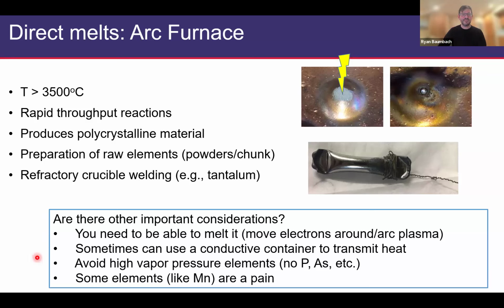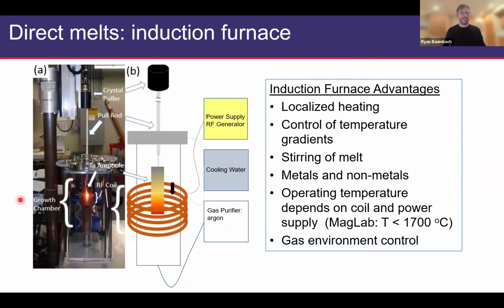And then some elements like manganese actually turn out to be a pain. This is because dirty manganese doesn't shatter when you put an arc on it, but clean manganese does. So in other words, if you arc melt it once, it tends to go well. If you arc melt it twice, it tends to shatter. I don't strictly know the reason for this, but I think it has to do with the different ways that the thermal expansion works in a dirty piece or a clean piece. So there's a lot of tricks of the trade, and you can learn about that if you just ask around and talk to people.